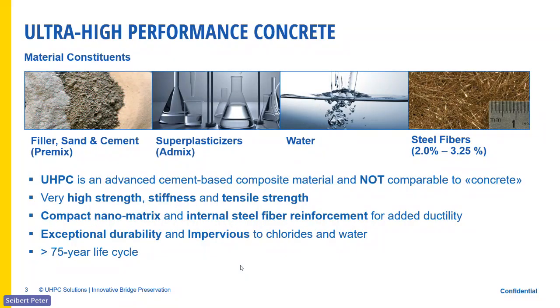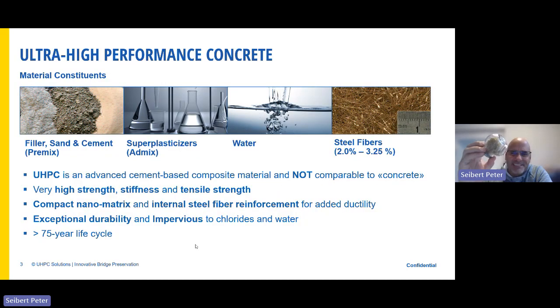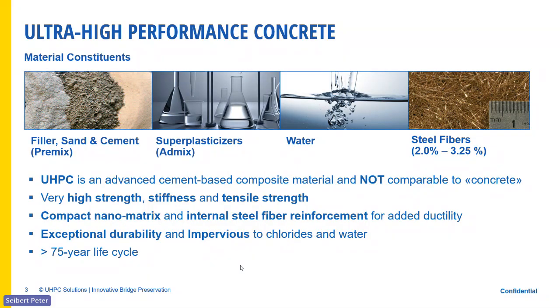So basically, you have the premix. You add super plasticizer, water, and fibers. Show those two again. Sorry, it's the last one. You can flip over to me. That's the fibers, and they're like little syringes. They're very fine. They kind of clump together, as you can see. They're 1/2 inch length and 0.002 inches in diameter. So these materials are getting mixed together, and you have a very dense matrix and a very dense material with tensile properties.